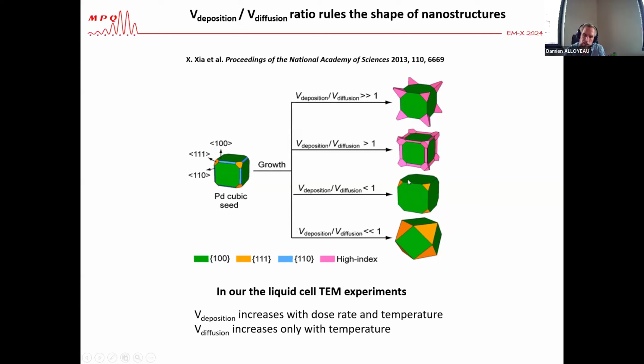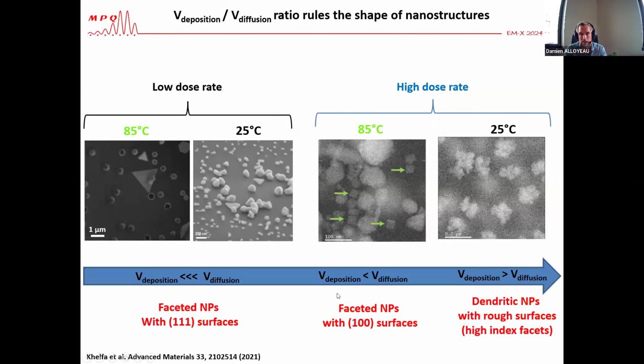And what is interesting in our liquid cell TEM experiment is that we can actually control the deposition speed, both with the dose rate and the temperature, but the diffusion of atoms at the surface of the nanoparticles only depends on the temperature. So we have a way to play with these two parameters. And that's what we have done.